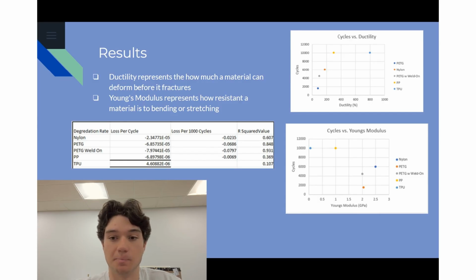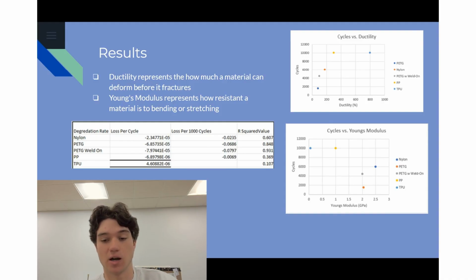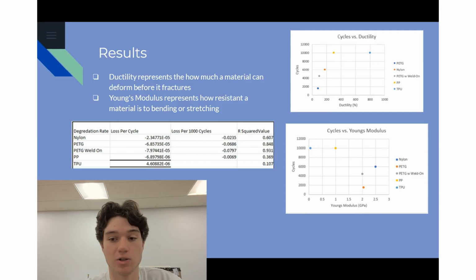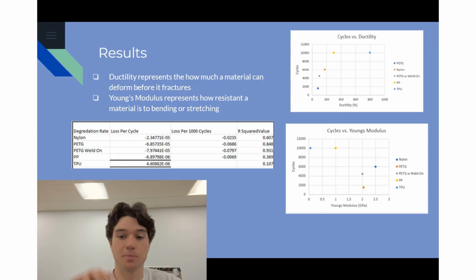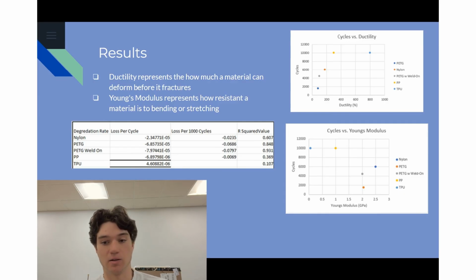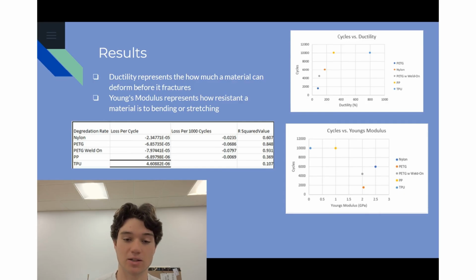As you can see, the nylon and the PETG are pretty low ductility, so they didn't perform very well. That's just one trend we noticed. And then for the Young's modulus, you want to have a relatively low Young's modulus. As you can see, the TPU and the polypropylene were pretty low. But the reason the TPU wasn't super ideal is because it was super flimsy and it wasn't super stable in both the bistable positions. And the polypropylene was almost too stable and it snapped too quick, which was its demise and ended up hurting it long run.